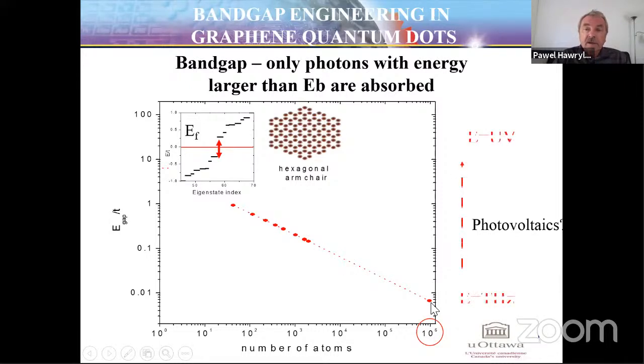And we see that we vary with T of the order of 3 electron volts, we vary the energy of the band gap from UV to terahertz. So clearly we could use such a structure for photovoltaics with highly tunable band.